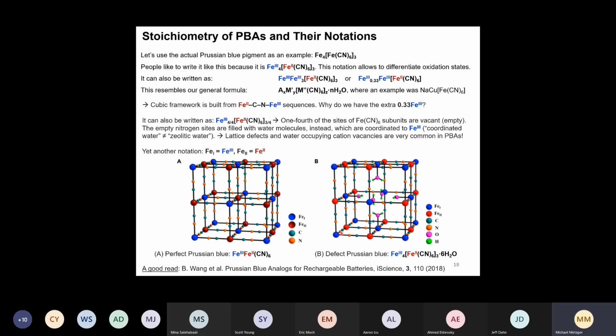But this is a stable structure, B, because the iron oxidation states and the cyano group oxidation state perfectly check out to be neutral, which is why this is a naturally occurring pigment molecule, this Prussian blue pigment over here. So I think this is a pretty stable structure, actually. And in a battery material, you of course don't want to have these coordinated water molecules. So you want to synthesize it in a way that you have charge compensating ions in all these sites. But I believe it would be stable in the B configuration. Okay, thanks.